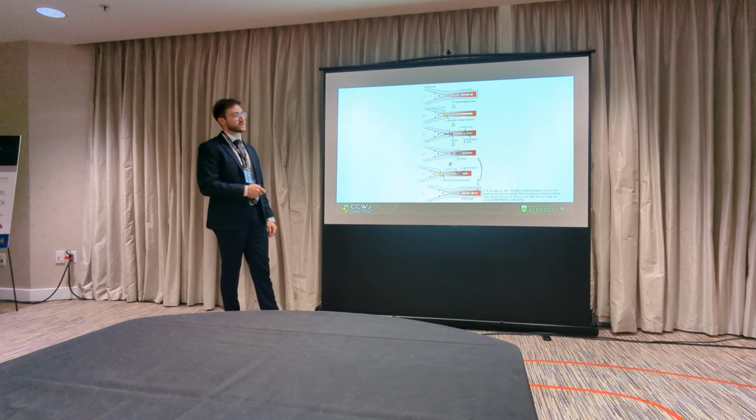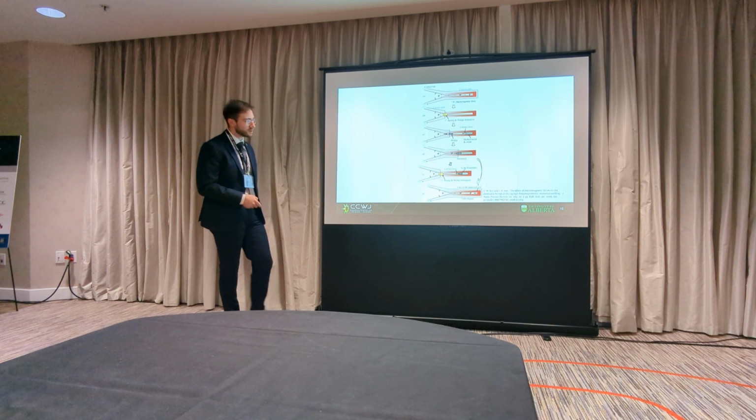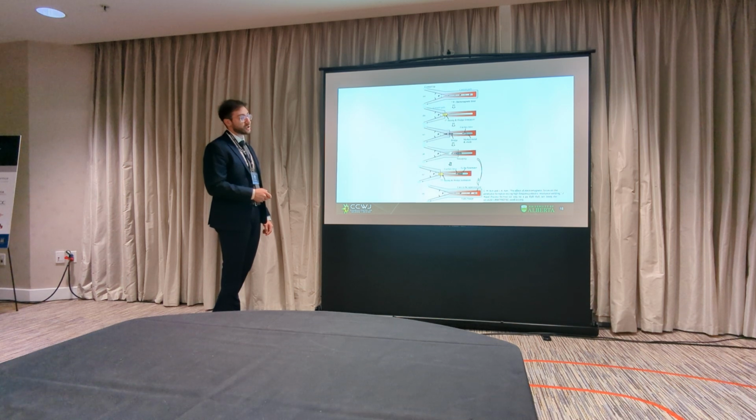And because this is a narrow slit, 2 things can happen. 1, you have pressure behind the bridge, so the bridge is going to move forward. And 2, capillary forces can allow this weld metal or this weld point to shift back up. Eventually, your bridge, which is the main point of your circuit contact here, meets the weld point.